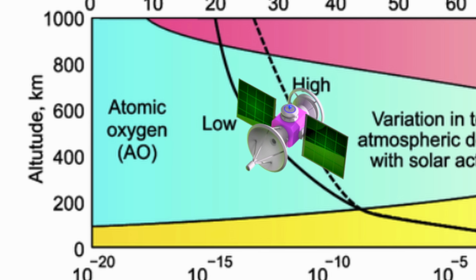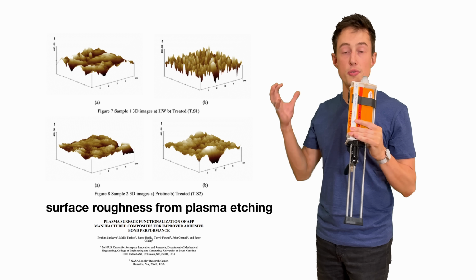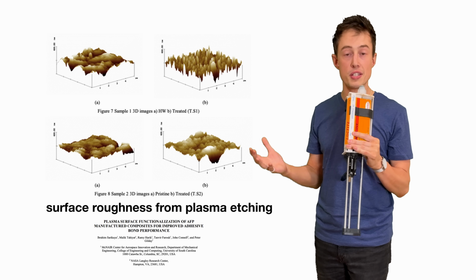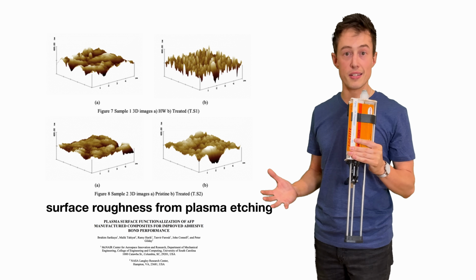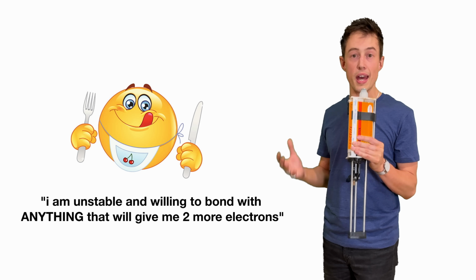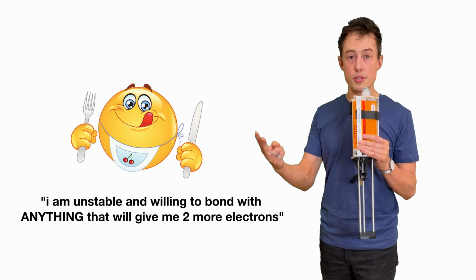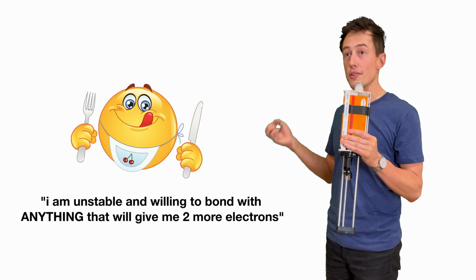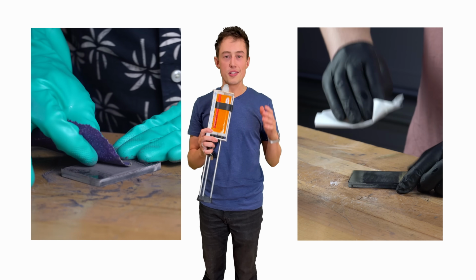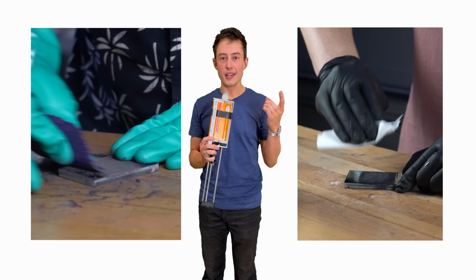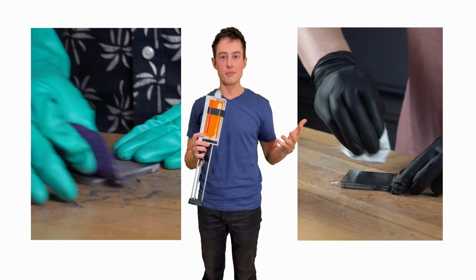So back to bond prep. We can use this atomic oxygen to etch away the material at a molecular scale, but we're also cleaning it. The hungry oxygen atoms want to bond with everything, which means they'll bond with oil, dirt, any contamination, and they'll carry it away. Atomic oxygen is incredible because it's like we're sanding and cleaning with IPA at the same time.